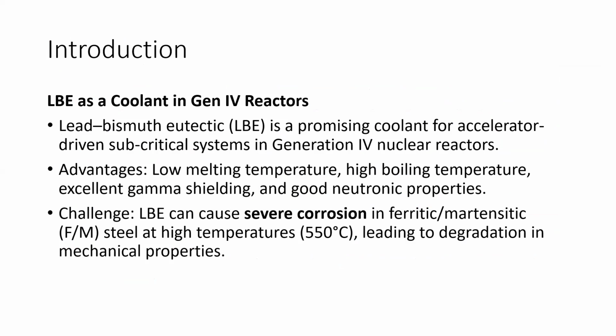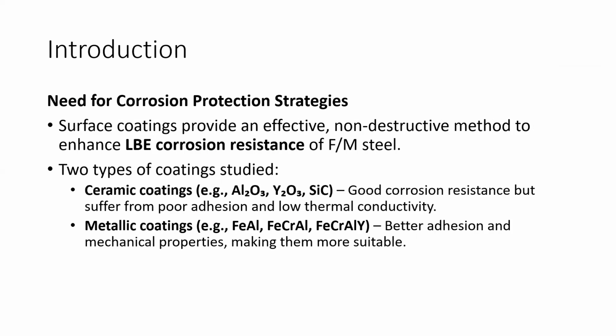So about the introduction, we know LBE is used as a coolant in Gen IV reactors. LBE is a promising coolant for accelerator-driven systems in generation IV nuclear reactors. Advantages: low melting temperature, high boiling temperature, excellent gamma shielding, and good neutron properties. Challenge: LBE can cause severe corrosion in ferritic-martensitic steel at high temperatures, like 550 degrees Celsius, leading to degradation in mechanical properties. So, there is a need for corrosion protection strategies.